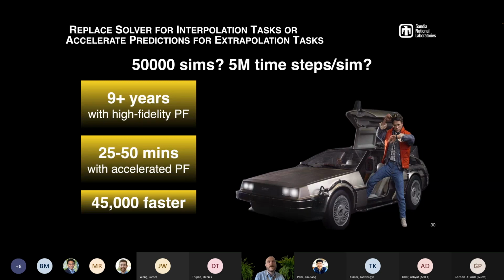But with our accelerated machine learning engine, it takes us about 25 to 50 minutes to do 50,000 simulations for 5 million time steps. So if you do the ratio between the two, you basically get an acceleration of about 45,000 times faster, which is again pretty impressive. And you know, there's a lot of things that you can improve on.